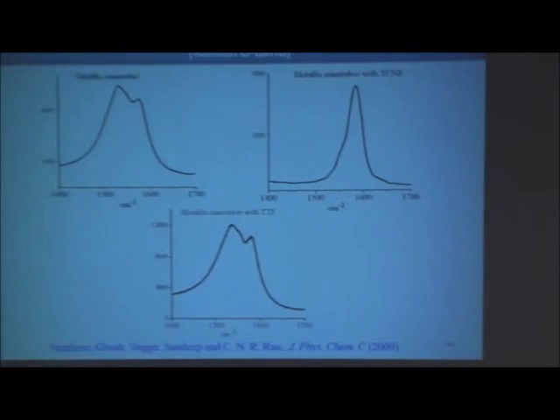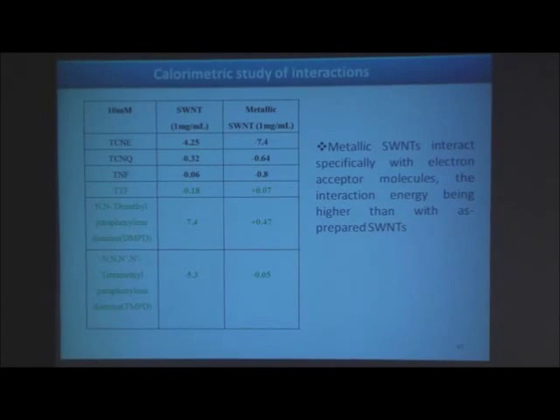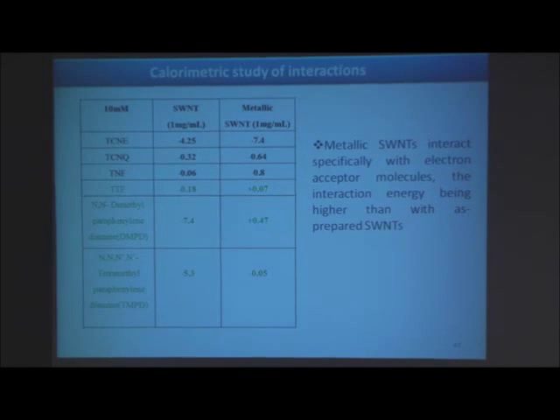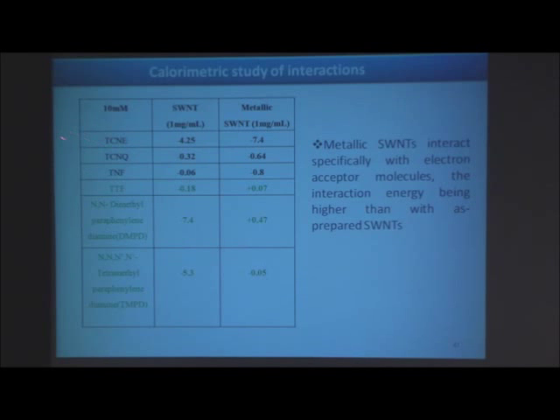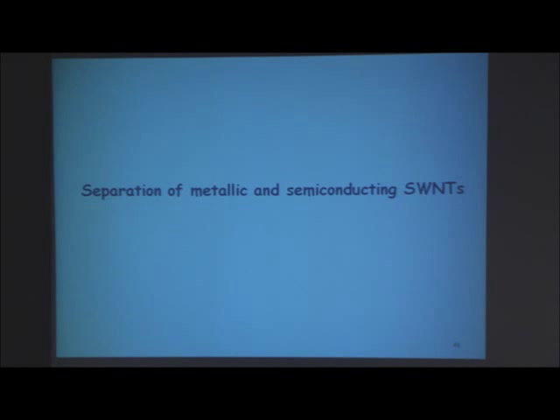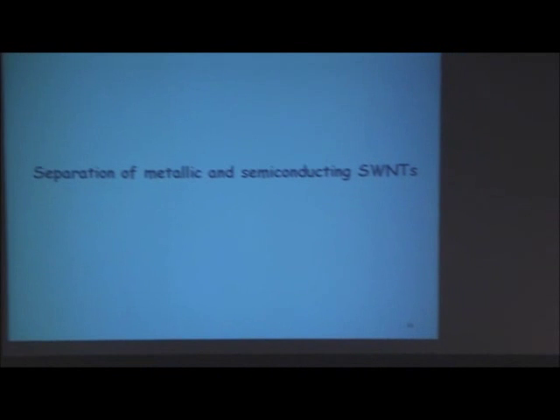And this is the variation of the bands, how they vary with donating and withdrawing molecules. And the same with Raman bands, how they vary when I put these molecules. And we have also proved by calorimetry that metallic nanotubes interact more strongly with withdrawing TCNE molecules, and the opposite, semiconducting nanotubes interact more with electron donating molecules. And based on that, 3 months ago, we had a very major discovery in our lab. Just one communication has come in Journal of American Chemical Society a few weeks ago. That is separating the metal and semiconducting nanotubes.